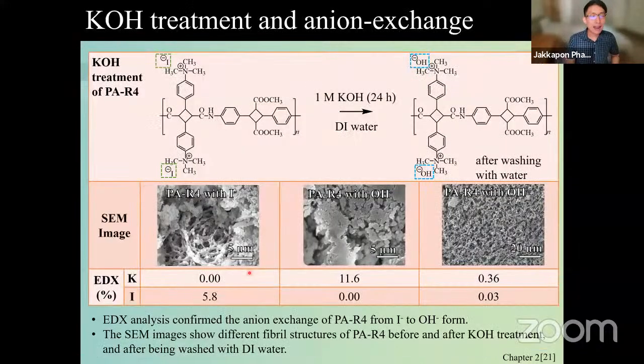Here, I have to convert the polymer into the hydroxide form. In order to do that, I just submerge it in KOH for 24 hours. And this is the commercialized form which we can use to remove iodide. This can be used to remove radioactive iodide too, but for the sake of my study, I need to use OH minus so that I can study it nicely, okay?